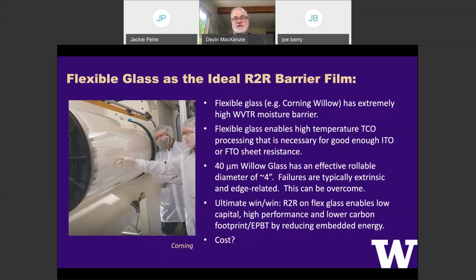And it touches on several things. Of course, it's thin. 40 micron Willow glass has a rollable diameter of 4 inches, which is quite good. Good enough for most roll-to-roll systems and most processing. It's right on the edge. And the failures are actually typically extrinsic. They're not intrinsic to the glass. It might have something to do with edge defects. It might have to do with shearing, but really extrinsic mechanisms, not the fundamental flexibility of the glass per se, or robustness of the glass itself. I think it can be dealt with from an engineering perspective. It can be overcome. Once we swallow this pill, there are some really great things.